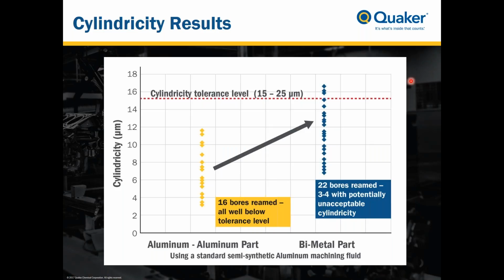If you go to the bimetal part, the aluminum powdered metal part, you can see of the 22 bores reamed, two results. One is that the cylindricity is notably degraded and worse than it is for the aluminum part. And actually, if we would consider a tolerance level up around 16 or 15 microns, you could see that some of the bores reamed might be approaching an unsuccessful level. So basically, as we would expect and as we saw, the reaming of the bimetal bore presents some considerable challenges and does give some poor quality.